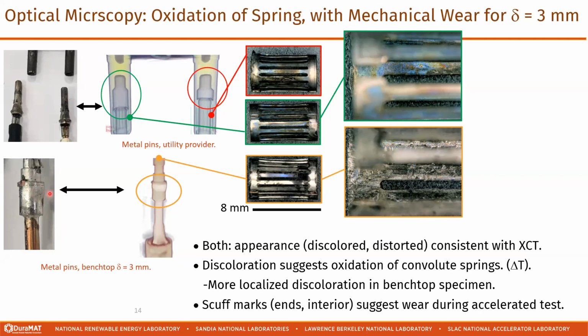Yes, indeed, there is a deformation in the solder area. And then if you extract the convolute spring, here there are broken ribs and also some scuff marks on the ends. And then if you compare the inside of the convolute spring, that looks like there's some wear that's been occurring relative to the field failed samples, where you just see the discoloration, presumably from the oxidation, right? And so the big takeaway here is that we think that there's some sort of mechanical wear going on. This was from one of the earlier samples, right, with the larger deflection, by the way.